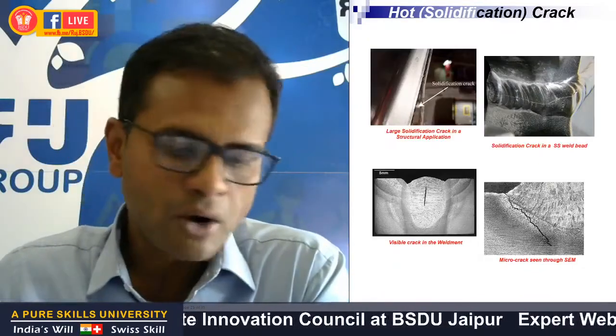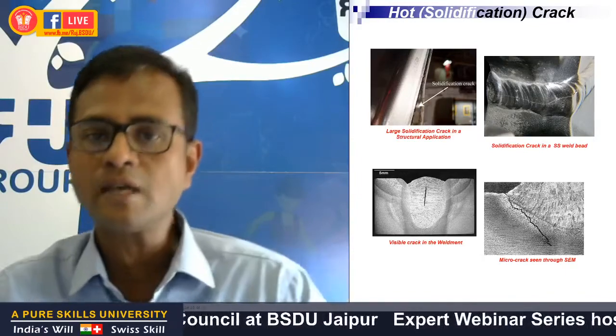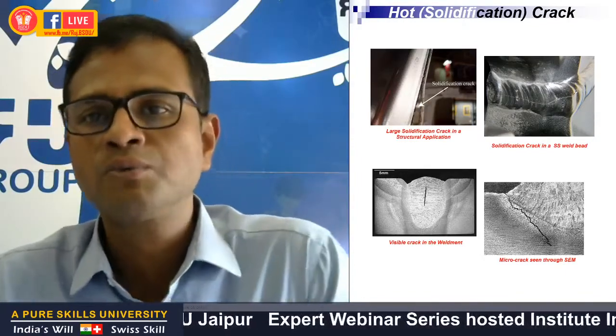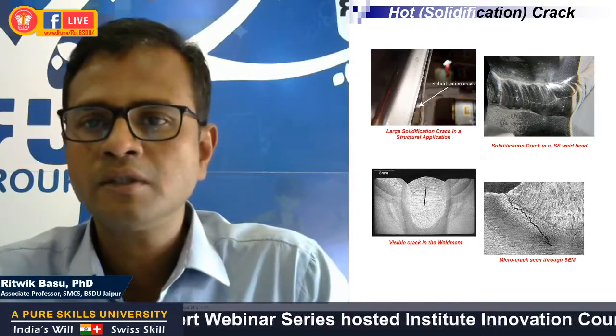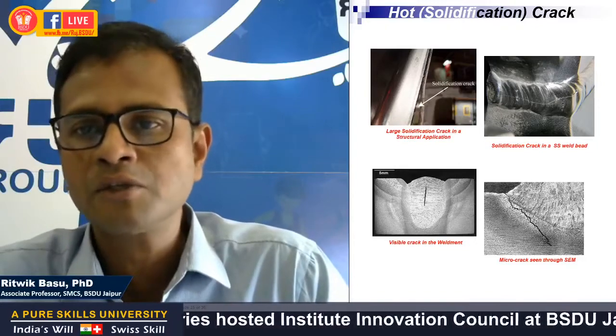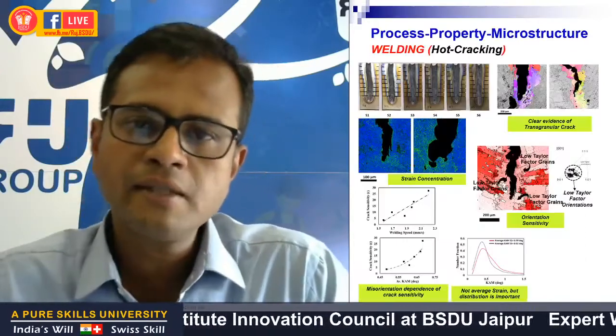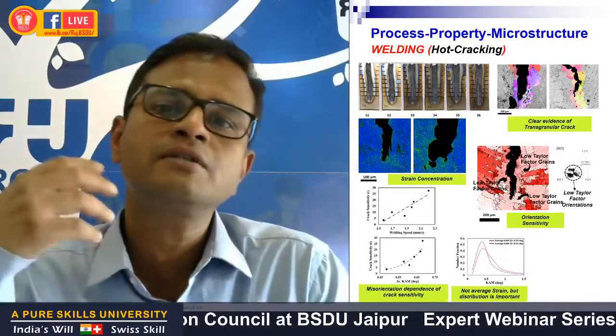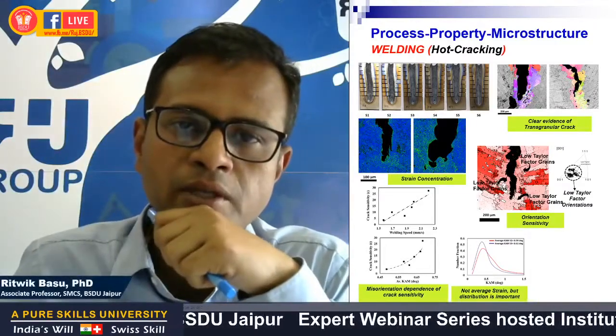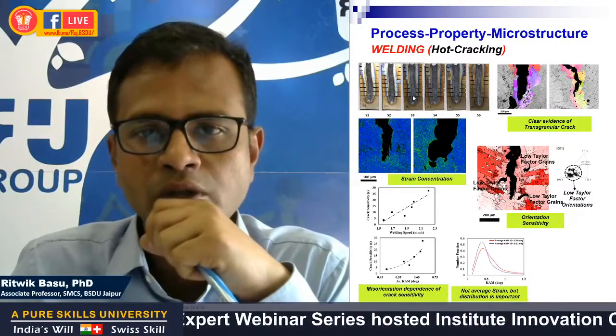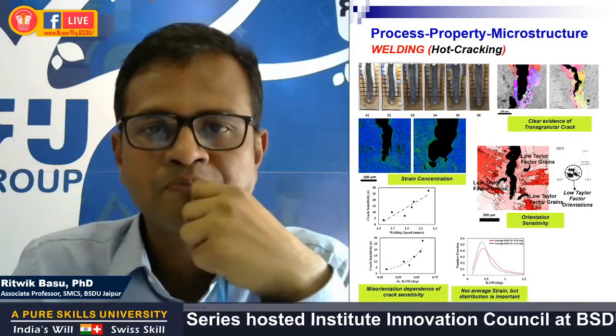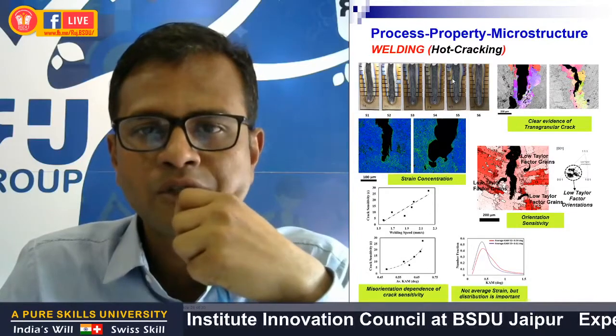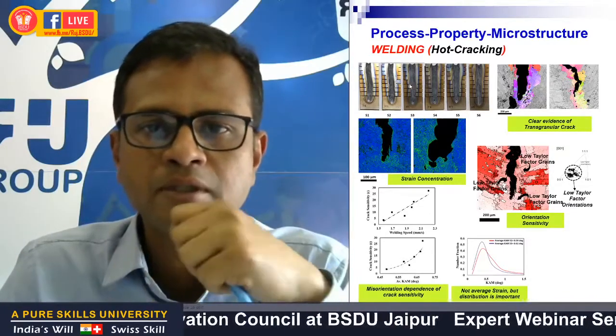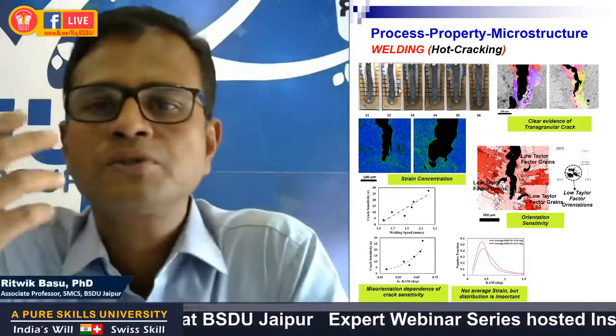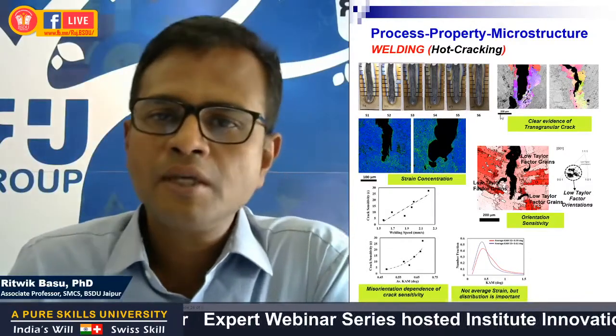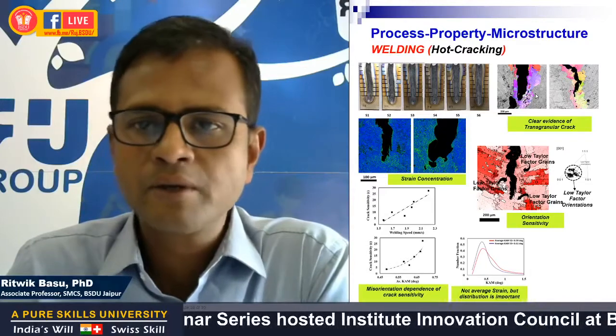Now, another problem that industries face when welding stainless steel structures is solidification cracking, or what we call hot cracking. It is actually the formation process of shrinkage cracks during solidification of the weldment or weld metal. So we have done a detailed microstructural analysis to investigate the reasons for solidification cracking in stainless steel welds. We tried to simulate these hot cracks in lab scale samples at different welding speeds. The morphologies of the cracks were pretty different between the samples, and these differences were also seen in the microstructures of the weld regions around the crack areas. The EBSD mapping revealed that these cracks were mostly transgranular in nature.